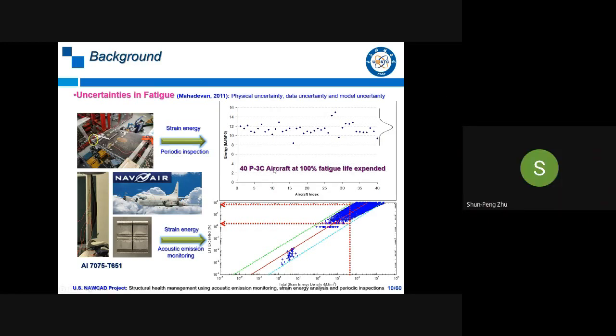And about this scatter, we can see here that for the exhausted energy, it shows a scatter. Also, in the laboratory test, we tested this aluminum alloy, and we used strain energy and acoustic emission monitoring. We tried to plot the total energy density exhausted during the cyclic loadings, and for the different life points we can see that the life ranges from nearly one cycle to 100%. So its life scatter is very large.